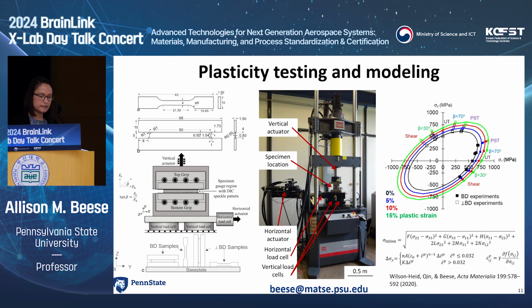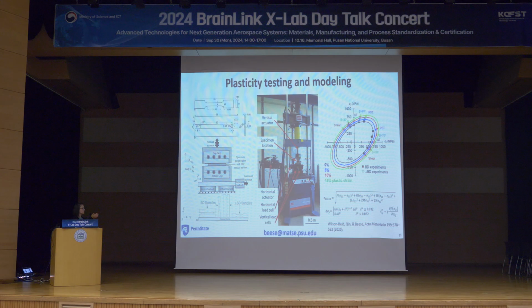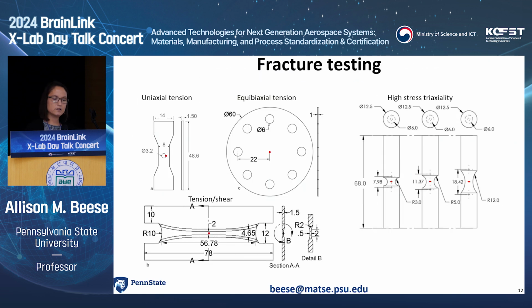And I won't talk about the details here, but for plasticity testing, we're able to match our experimental data, which are the points, with a computational model, which are the lines, and we're able to describe how the material initially yields, which is in black, and then how it flows with increased plastic strain, which are the colorful rings after that. So we can put this in a finite element analysis code so that we know how the material deforms. And the next thing then is to say, well, what about how it fails? And so when we think about failure, there are some experimental techniques that we'll apply so that we can understand the failure behavior.